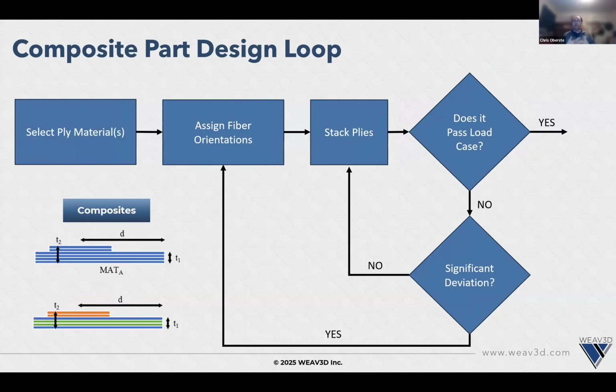When we talk about composites, it's a little bit more complicated. So we have the ply materials. You can have different types of plies in your composite stack up. You could have glass, carbon fiber, Kevlar, what have you. You also will have fiber orientations. So if you're dealing with a unidirectional or even a woven fabric, whether or not you're laying it down in the 0 direction or plus or minus 30, plus or minus 45, those will all have an effect on the mechanical performance. And then you're going to have your ply stack. So how many plies do you put in a given location? Do you have a constant thickness over the whole part, or do you have extra reinforcement in certain areas? So those are your three variables in that use case.